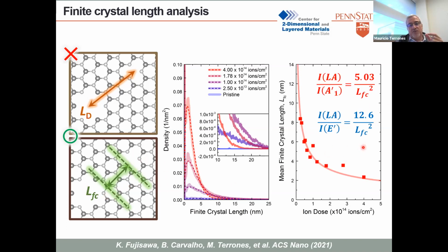And these are the formulas. If I calculate the intensity of LA and the A1 prime, I can get this finite crystal length, or if I do it with the E prime mode. So these are the formulas that people can use, and they can estimate how defective the system is. And I think this is quite useful.